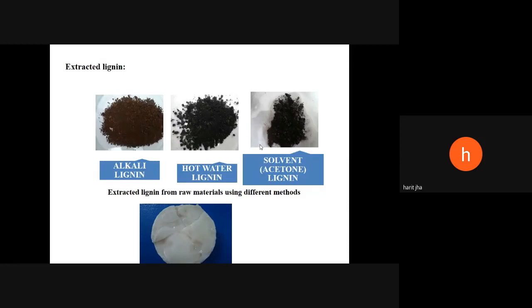During many of these treatments, our sole aim was to degrade lignin, or partially transform lignin, so that the lignin carbohydrate complex can be separated. And once the lignin carbohydrate complex is separated, the extraction of cellulose becomes a lot easier. It requires less chemical and less harsh conditions to remove and extract the cellulose.